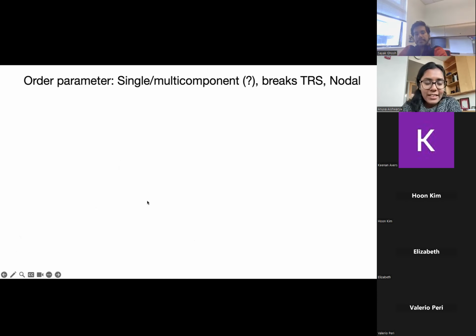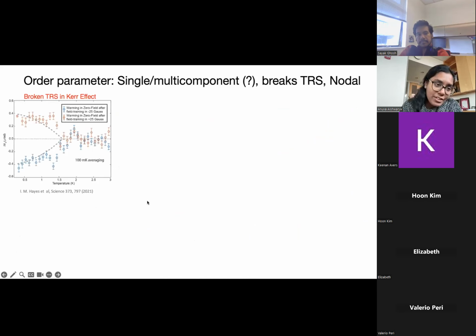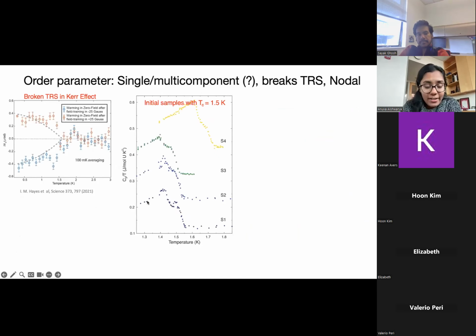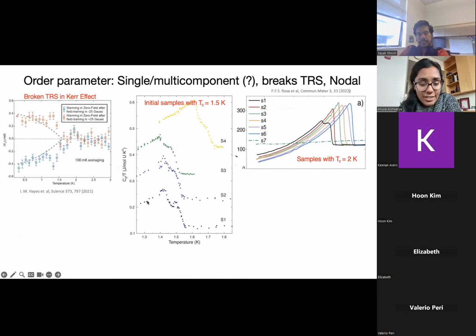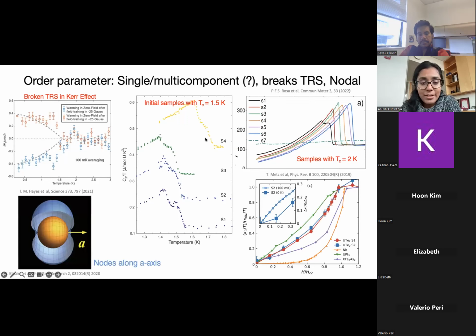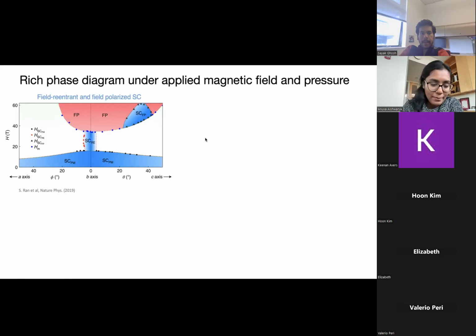So talking about the order parameter, I think it's still unclear whether it's a single or multi-component order parameter. Some initial measurements showed broken time reversal symmetry in the Kerr effect, and a double jump in specific heat, pointing towards a multiple component order parameter. But some more recent samples from Priscilla Rosa's group saw only a single jump in specific heat. Similarly, thermal conductivity measurements indicate a nodal order parameter, probably with nodes along the A direction. It also exhibits a rich phase diagram in magnetic field. There are multiple re-entrant superconducting phases and field polarized superconducting phases.